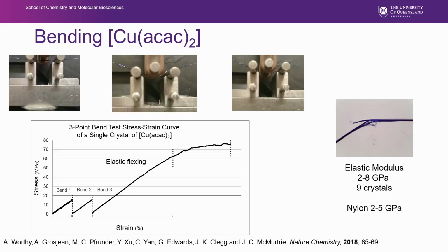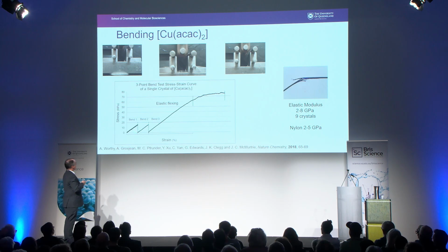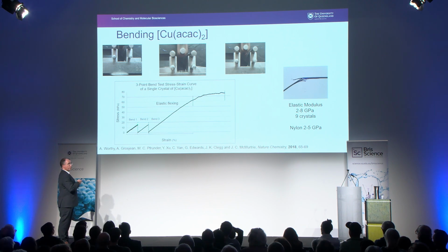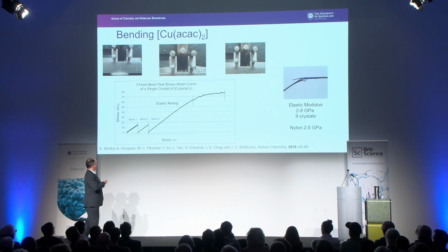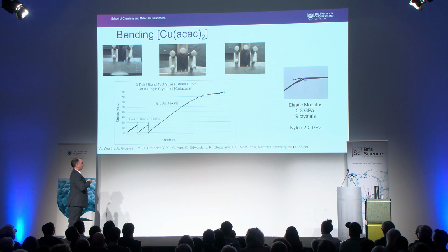You can't just stretch these things. Of course, we've seen we can bend them, but how far can we bend them? And to do that, again, our engineers have wonderful things called a 3-point bending test. So we take our crystal and we apply a force and we measure how far that force goes down. And so what we've done here is just taken one of these crystals, we've applied a bend, and then we've removed the force and done it over and over again to show that it's elastic. Not only is it a straight line, but it is also reversible.